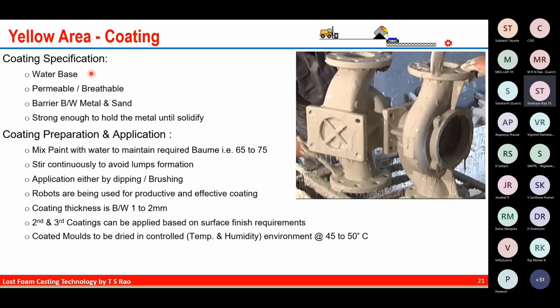The paint should be permeable so that it is breathable, and it will act as a barrier between metal and sand, and it should be strong enough to hold the metal until it solidifies. For the coating preparation and application, mix paint with water to maintain the required Baume. It is about 65 to 75, and stir continuously to avoid lump formation.